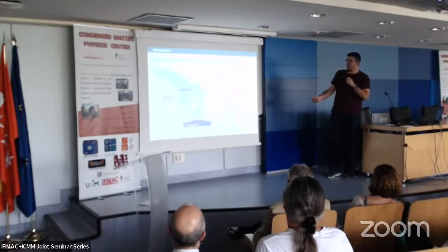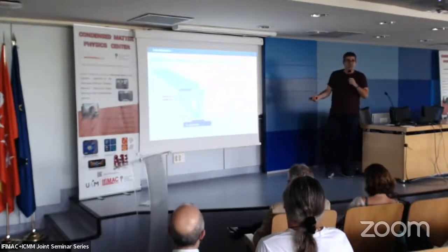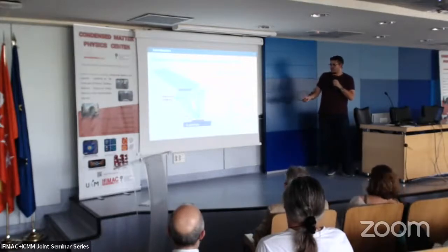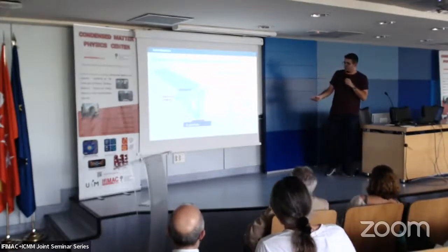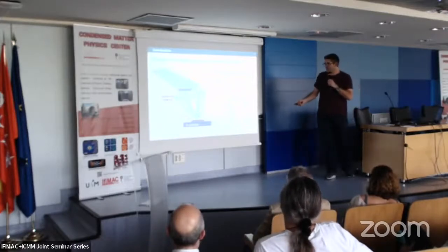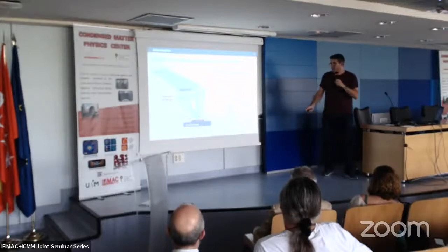What happens now if we look at an atomic force microscope with a diamond tip? We can see it as a nanotechnology version of one of these diamond anvil cells. If we see the pressure as the force over the area, considering our tip radius, which is very small, with moderate forces we can apply very high pressures. We can estimate that, and reach an expression where we can directly relate the pressure with the force. So by controlling the force, something we can do very well with an atomic force microscope, we can control the pressure very precisely.